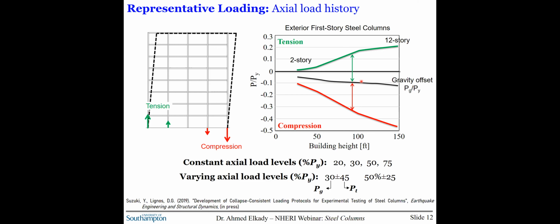So based on this evaluation, we chose a number of constant and varying axial load ratios to employ in our tests. If you look here, the varying axial load essentially includes a constant component representing the gravity offset, or what we call PG. And then you have a transient component representing this variation due to the overturning moments. And for the constant axial load, we went from 20% PY up to larger axial load levels of 75% PY, which may actually be representative of columns in older constructions.